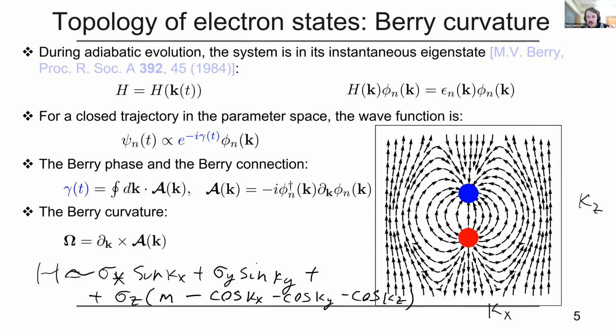For sound dichroism, perhaps it would require a break in time reversal symmetry, because if we want to create the pseudomagnetic field, we need to break time reversal symmetry in the material. So there probably these cobaltate compounds might work. For just measuring sound attenuation, any Weyl or Dirac material should work, I would say.